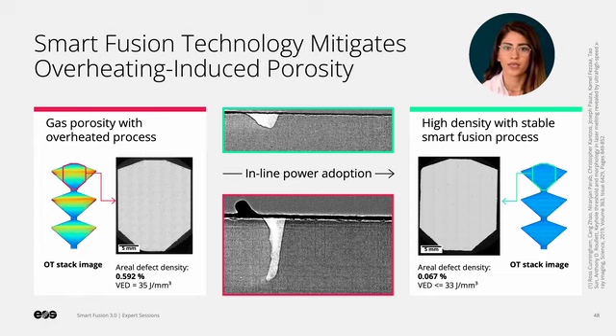Comparing the porosity level that has been measured by the areal defect density from the cross-sectional image shows a 10 times improvement in porosity level, from approximately 0.6% in the sample built without Smart Fusion to 0.06% in the sample built with the applied Smart Fusion.